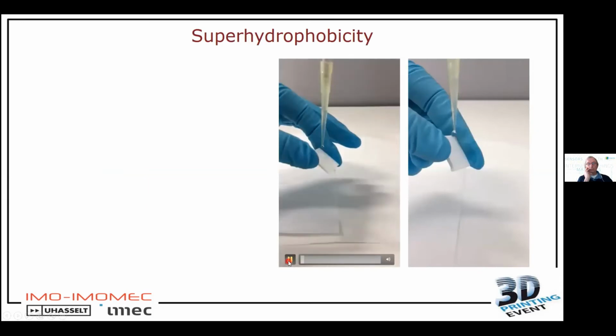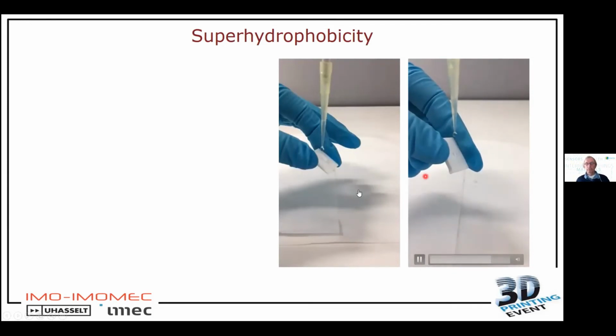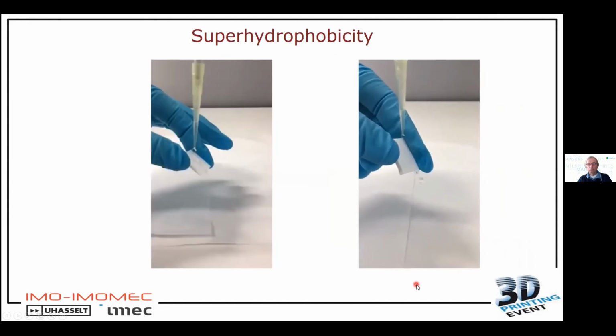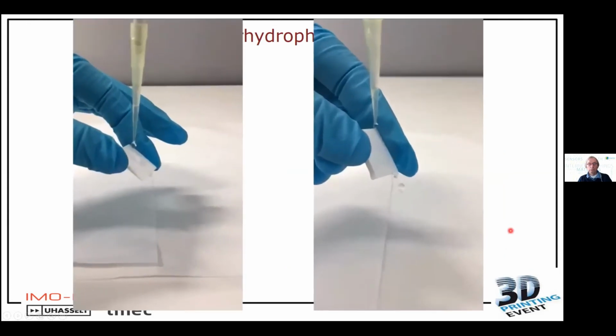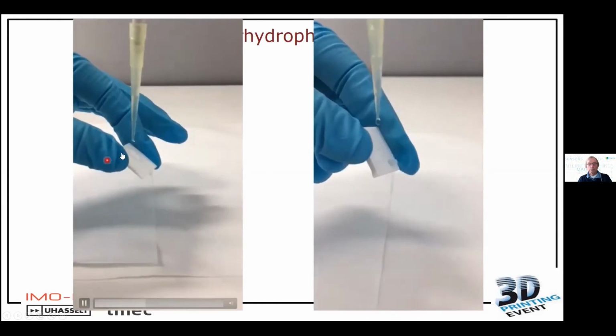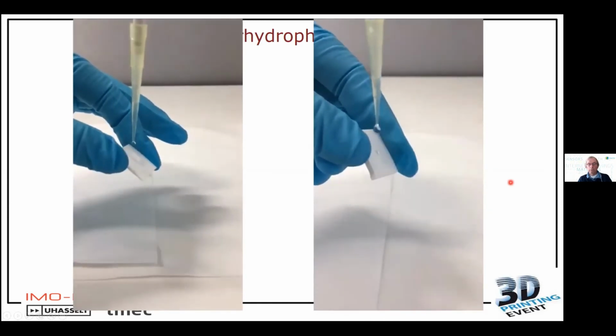Here you see the contact angle of a droplet, which is sprayed on a normal substrate without these nanoparticles. I don't know if it's very clear, but you see that the drop stays on the substrate. While on this one, you see that the drop just rolls off. So this is a clear view that we have increased the contact angle up to 150 degrees and have this easy to clean substrate. So that's, let's say, the biggest difference between both. Here you see it again. So this droplet sticks and this droplet easily flows from the substrate using these nanoparticles.